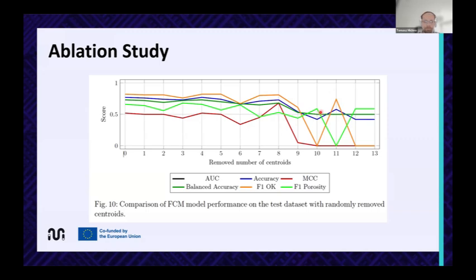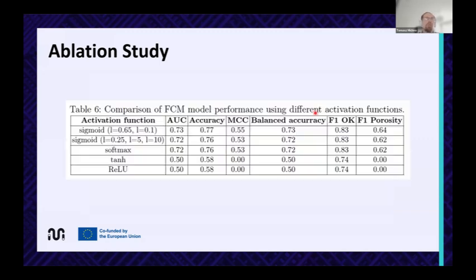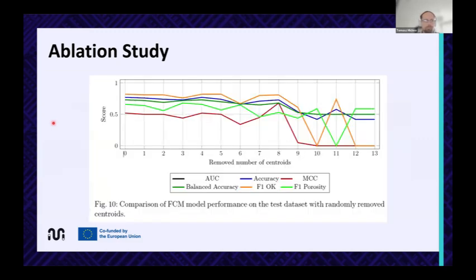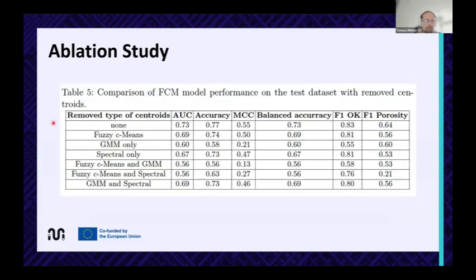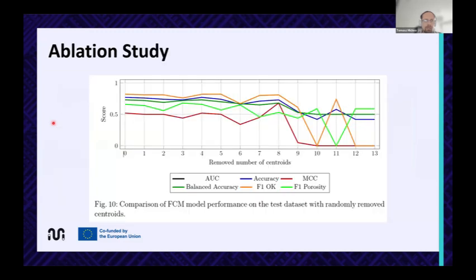We also checked different types of activation functions in the fuzzy cognitive map. And we can see that some of the activation functions work quite well. And the results were quite similar, but for example, for TAN-H or RELU, the results were not the best. As we can see, the MCC was equal to 0, so the classifier was not working correctly. So it's also very crucial to choose the right activation function. And yes, this slide already shown.